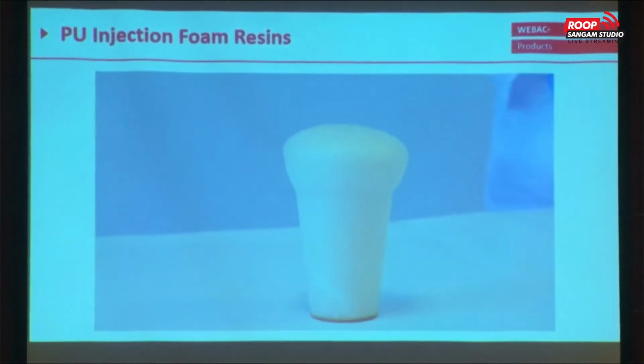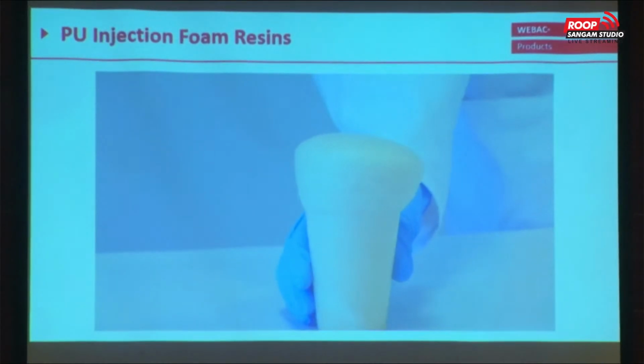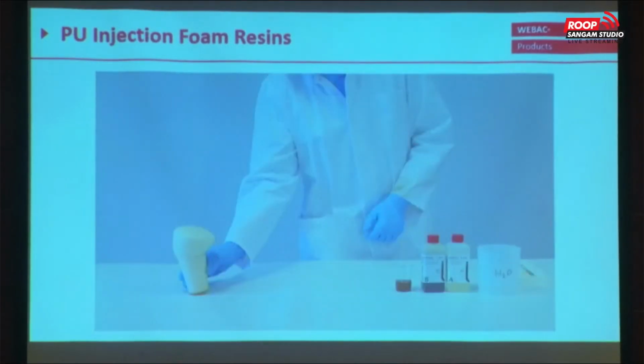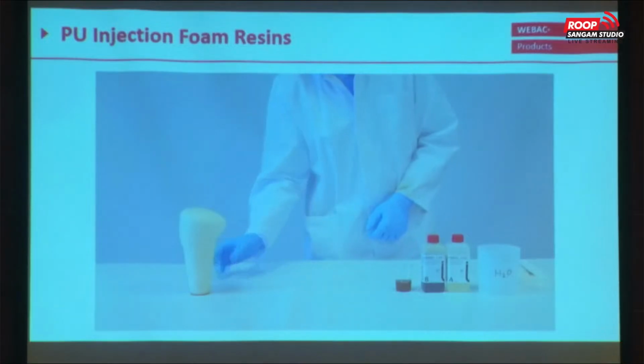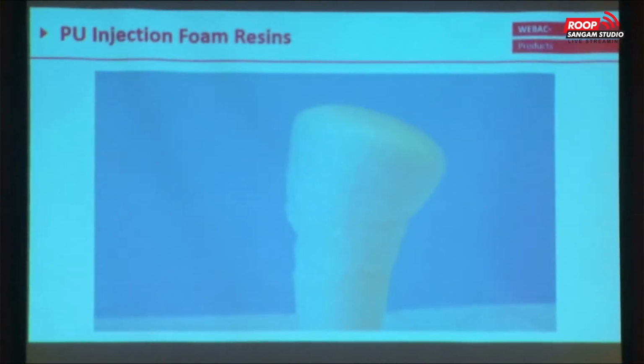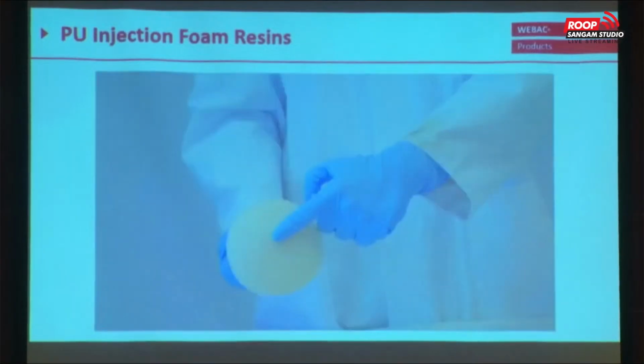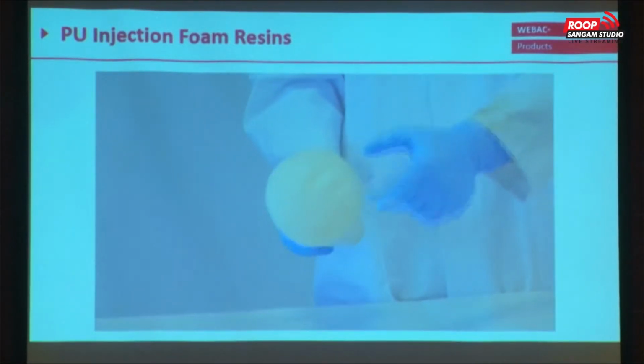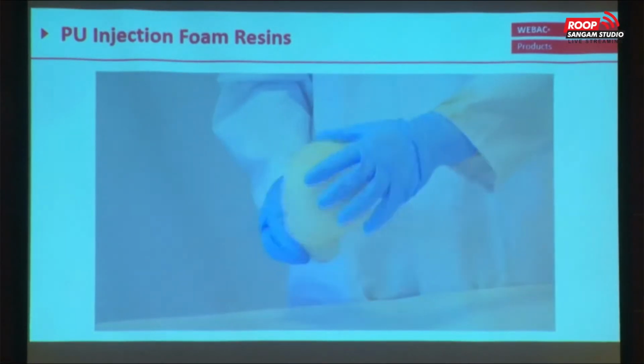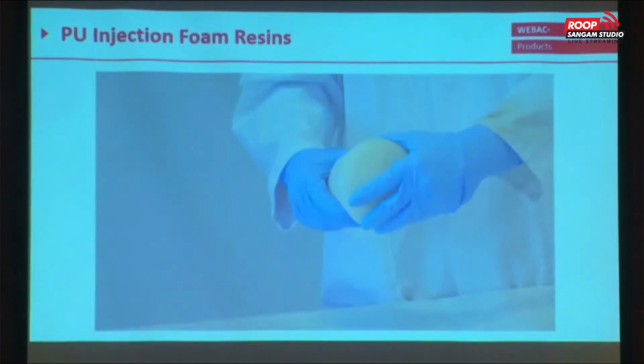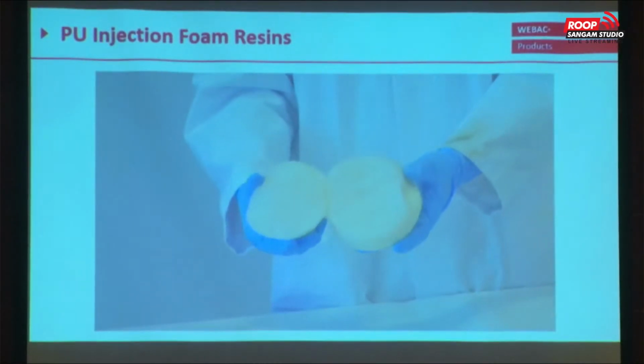Now we have roughly, I would say, a foaming factor of 40 times, depending on the mixture, on the turbulences. And my colleague will open now the foam so that you see the fine pores, the fine structure, which pushes the resin also deeper in the soil. So it's really brittle after a couple of seconds, and he will open it. And it's a fine open cell pore structure.